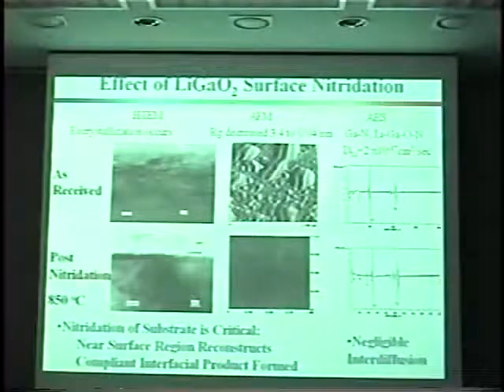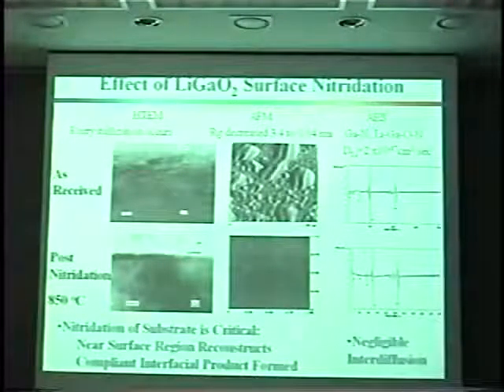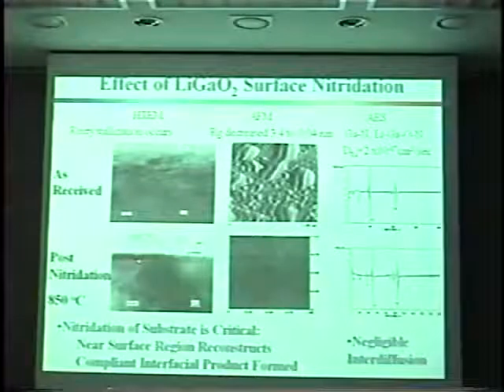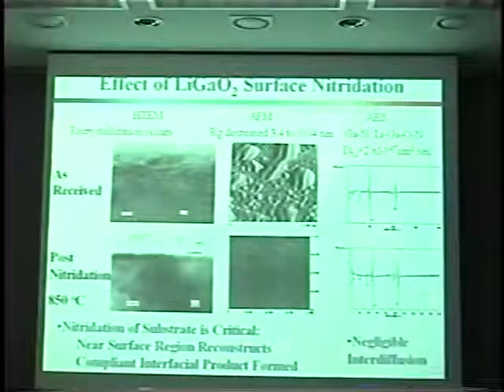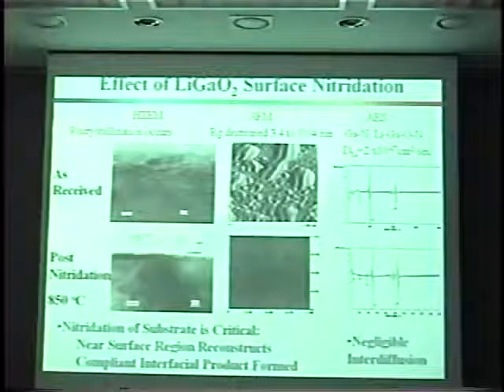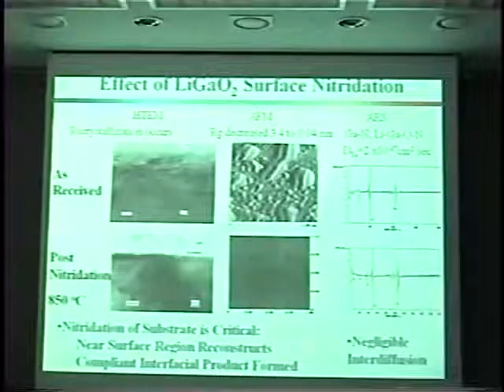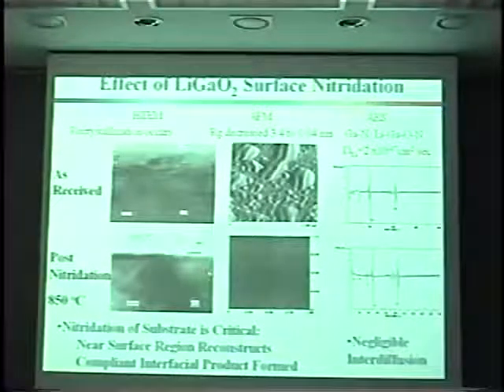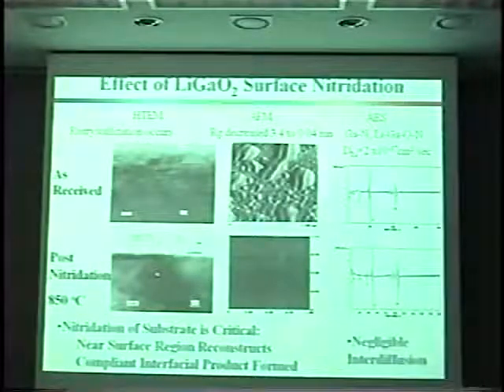However, we found that if we did a nitridation of the interface, and this is the LGO, this is an interfacial layer, and then we would have gallium nitride going on that. If we just did a nitridation of the LGO at 850 degrees C, we would form a very thin, on the order of about 20 angstrom, lithium gallium oxynitride compliant layer. And not only that, which is very unusual, we would see that the underlying LGO would actually grow epitaxially, most likely from deep in to the surface, to leave behind single crystal lithium oxy gallium nitride on top of single crystal LGO. And a real nice interface.